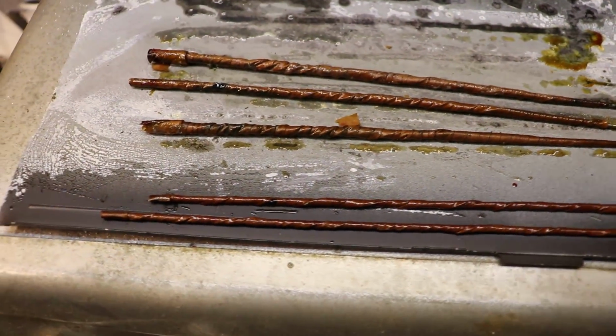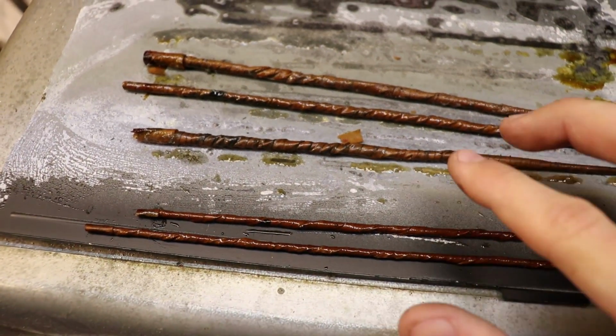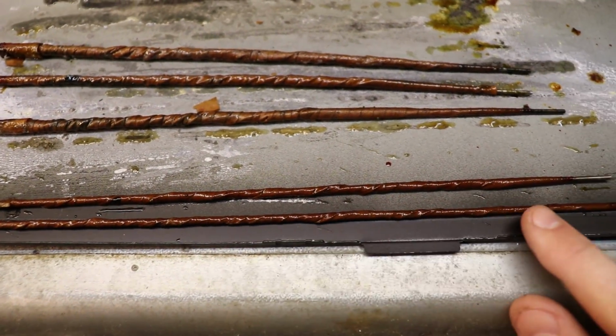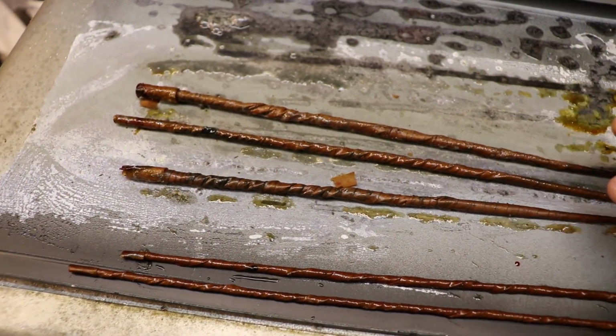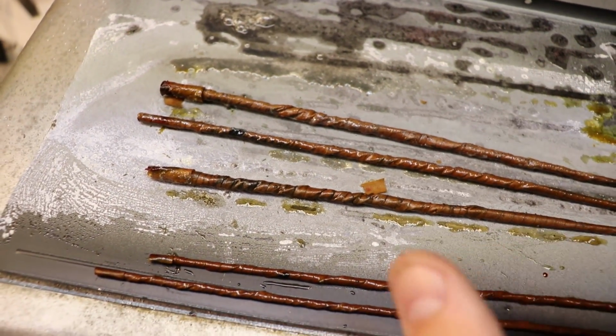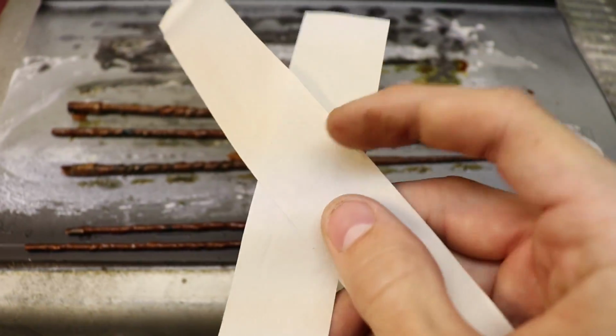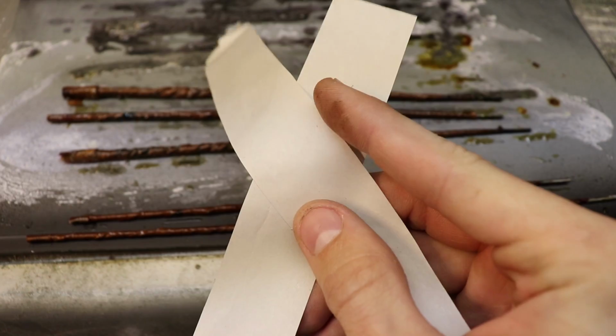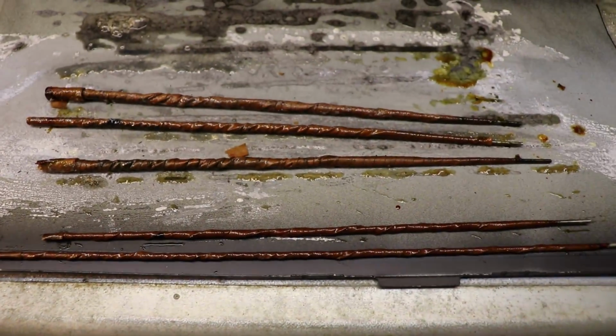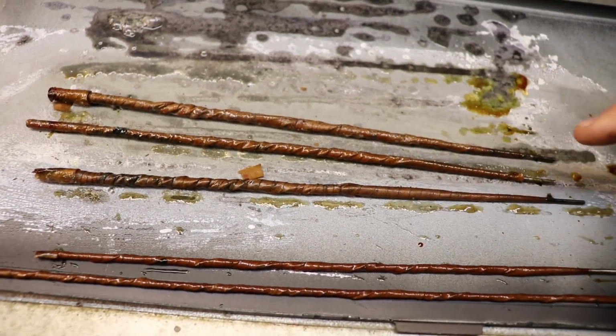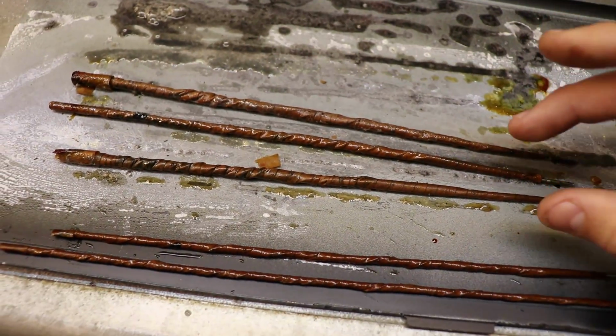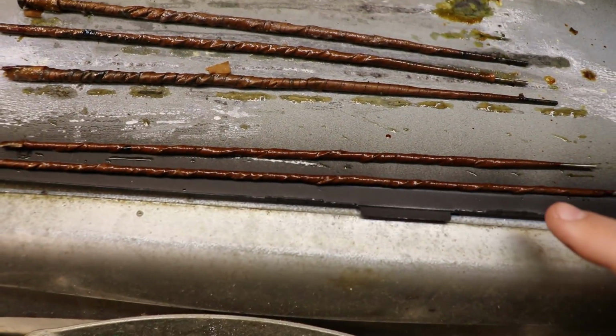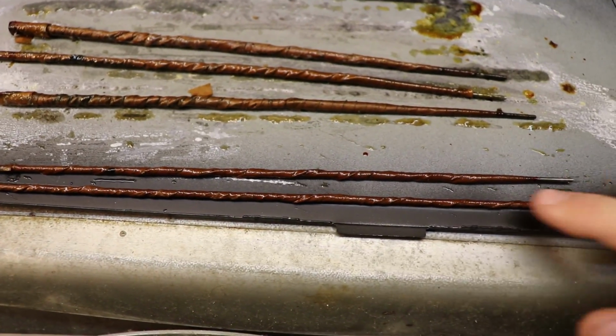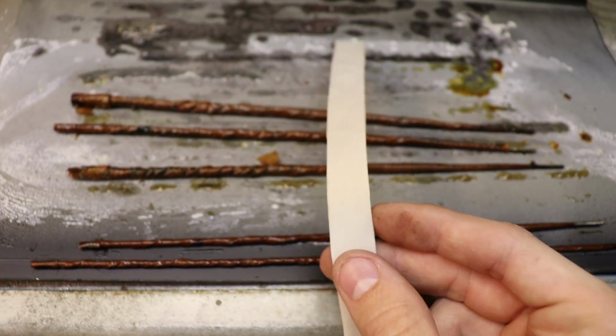So because of this, I think I'm going to actually reheat them and dry them out again before I start welding with them. Now the second thing I want to point out is that you can see a clear difference between the skinny ones here and the thicker ones. And the thicker the wrapping, or the wider the strip that you use, because I used these wider strips, which are about 1 inch wide. I used them on these 3 rods, and you can see how they turned out. There's less uniformity along these rods compared to these ones, and the skinnier ones I used about a 1/2 inch wide strip.